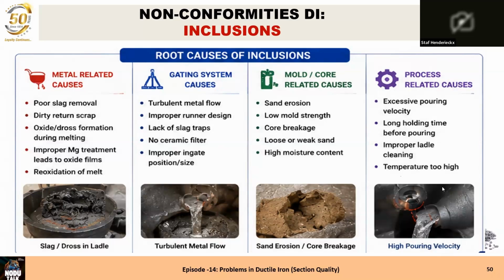The gating system: turbulent flow will cause dross, because one of the elements of dross is oxygen, magnesium, silicon, oxygen, and the turbulent flow provides oxygen, and therefore you make dross. Improper runner design, that's the same. When the metal speed in the ingates is very, very high, you will get again this turbulent entrance of the metal in the casting, and that will be forming dross. The lack of a slag trap. One thing is very important, and I see it all over the world. Every runner should have a slag trap at the end and under the sprue.